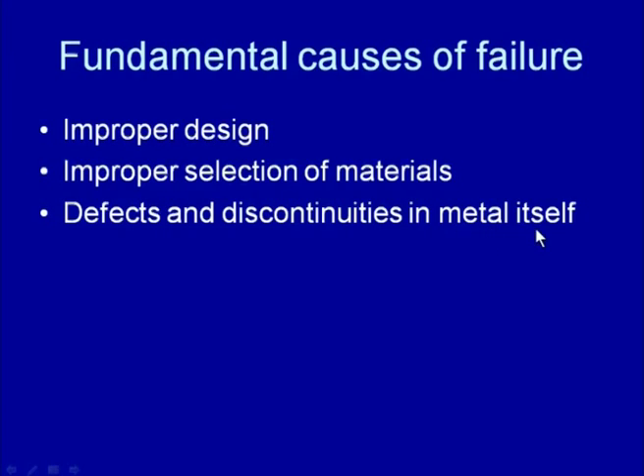So, those factors lead to improper selection of the material for development of a particular component. Another factor is defects and discontinuities present in the material itself, meaning the material being used for developing a particular assembly or component is defective and inherently has discontinuities, like the presence of inclusions in large quantity in steel sheets causing lamellar tearing. Those are the kind of problems related to the presence of discontinuities in the metal itself. Similarly, a high amount of hydrogen in dissolved state in steels can contribute to hydrogen induced cracking in weld joints made of hardenable steels. Those are the defects or undesirable features present in the metal itself and contributing significantly towards failure of the component.